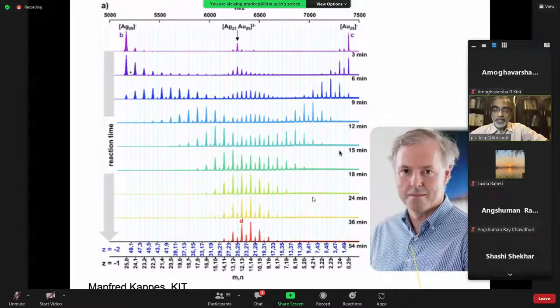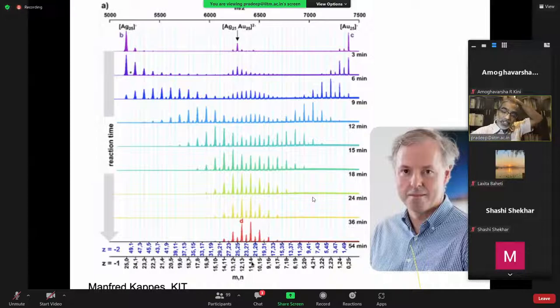But at the end of these, or as the reaction proceeds, you start getting a large number of other dimers as well. You see that in between each one of these peaks, which are atom exchange peaks, you also see dimers. So these are dimers, whereas these are atom exchange products. Let us say this is Au12Ag13, and this peak is Au11. Oh no, this is Ag11Au14. And the dimer here is falling in between that.